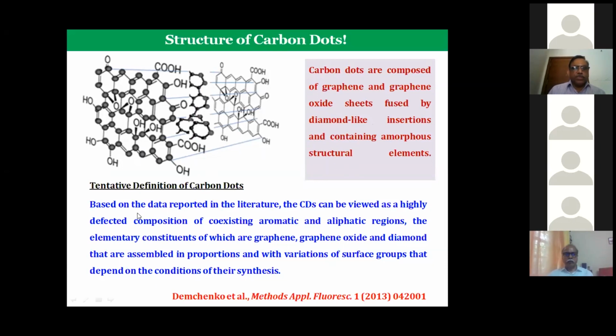Based on the literature available, the carbon dot can be viewed as a highly defected composition of coexisting aromatic and aliphatic regions. So we have the graphitic and the diamond-like structure. This is the basic definition one can give for the carbon dot structure.